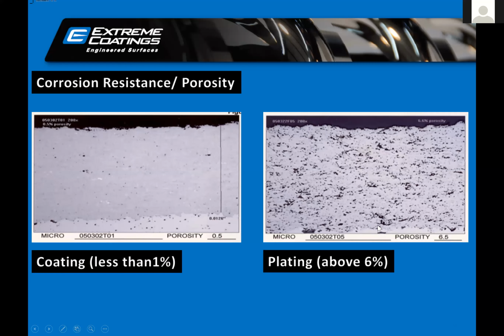Chrome plating porosity is actually more than 6%, and that's why sometimes you hear that some suppliers use triple chrome plating, because one chrome plating is not enough. It may have a lot of porosity, while in coating the porosity is almost less than 1%. In fact, it is 0.5%.